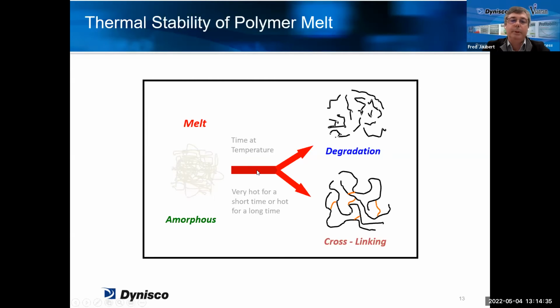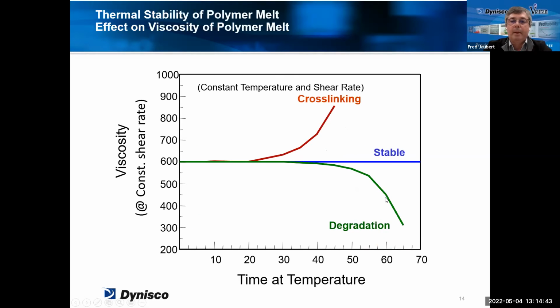So this is just another way to show it. So basically, with time and temperature, you can get either degradation or cross-linking. And the result on the viscosity curve will be like this. If you have cross-linking, the viscosity is going to increase. If you have degradation, it's going to decrease, obviously. And if you have a stable product, you should not see any noticeable variation of the viscosity over time.